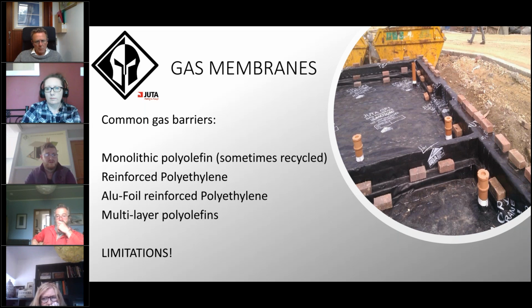Then we've got, which is a very common breed of gas membrane at the minute, the aluminium foil reinforced polythenes. This was primarily driven by the change to BS 8485 in 2015, where we dropped in the gas transmission rate as a benchmark for manufacturers. So we all raced to test our materials, and we found that we were looking at aluminium as the most reasonable course of action in the short term.